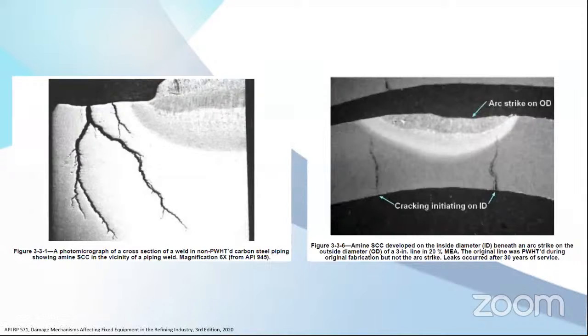This is the example of amine stress corrosion cracking. The first one is when it's not post-weld heat treated, so this is the area where you have very high stress, and it's cracked. And the second one is from an arc strike. This is also very high stress in this area, so the crack initiated from this area. And this leak occurred after 30 years of service.